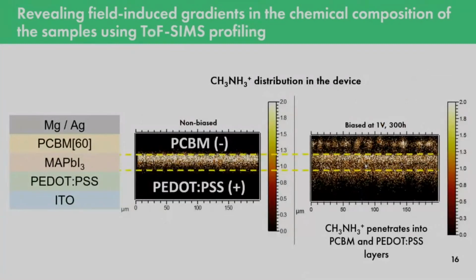To understand better what's going on, we decided to go back once again to the solar cell and to check the same solar cell that was used in previous measurements with TOF-SIMS. And we observed a very interesting point: after biasing for 300 hours inside the solar cell, the methylammonium cations penetrate into both charge transport layers, into both PCBM and PEDOT:PSS.